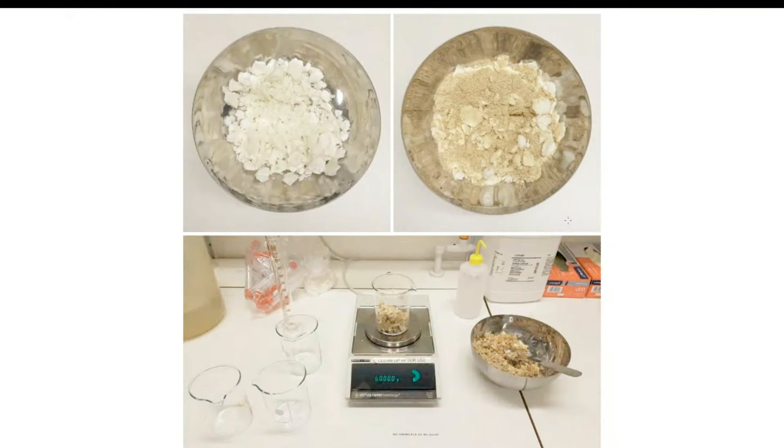The substrate is the base — a scaffolding on which the fungus grows and transforms. It's made of cellulose and wood chips mixed with water and a few thickening agents and some clay to make the process work better. Importantly, the fiber sources for the substrate can come from a variety of places, providing a great opportunity for integrating waste from different industries back into production, as well as sourcing locally since fibers are available in most biomes. Since it involves working with a dynamic element — the living fungi — these can adapt and evolve to grow on different substrates, which means it doesn't create a further need for monocultures.